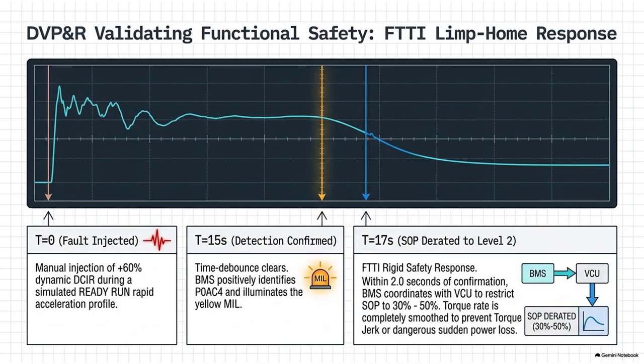And they don't just shake it at room temperature, do they? The shaker table is built inside a massive climate chamber. Yes. While the pack is undergoing continuous violent 3D vibration, the chamber is rapidly cycling the ambient temperature from -40 degrees Celsius up to +85 degrees Celsius. So they're freezing it, boiling it, and shaking it to death all at the same time. They are intentionally inducing extreme rapid CTE mismatch expansion and contraction while simultaneously subjecting the joints to high G mechanical fatigue. And how long do they do this for?